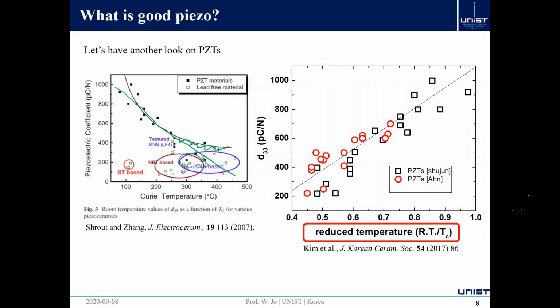And then I plotted everything again in terms of a linear line, but not just the Curie temperature, but the reduced temperature. I call it reduced temperature. Since the D33 value should be measured at room temperature, the points represent D33 at room temperature. That means we cannot really compare the room temperature D33 as a function of Curie temperature, but maybe as a function of reduced temperature, in this case room temperature normalized by the Curie point. Because at least in this PZT material, we don't have a phase boundary between TC and room temperature. So I just plotted them, and this line is not an eye guide. This is a fitting line. If you look at this fitting line, it fits very nicely with the linear line.